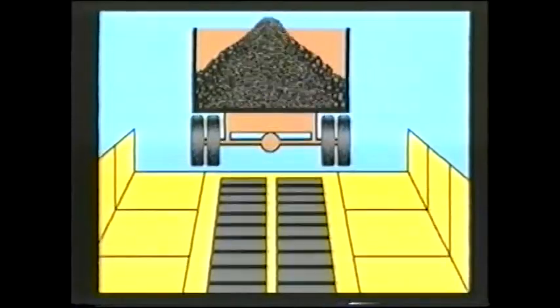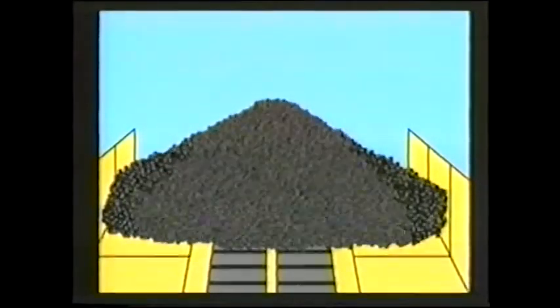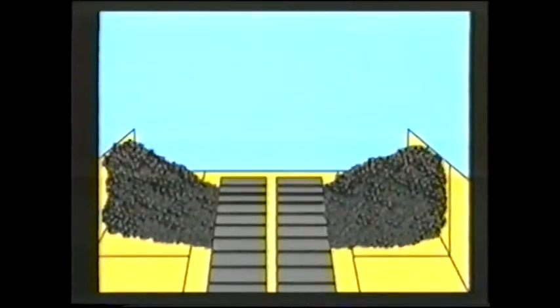When the truck unloads into the paver hopper, the larger aggregate remains along the outside wall. As the walls are raised to clean the hopper, the large aggregate goes in last. So the segregation that began in the slat feeder continues directly into the laydown process. With the asphalt industry moving toward large stone mixes, this silo design will cause even greater problems in the future. CMI Corporation, with its reputation for innovation, has tackled this problem head-on.